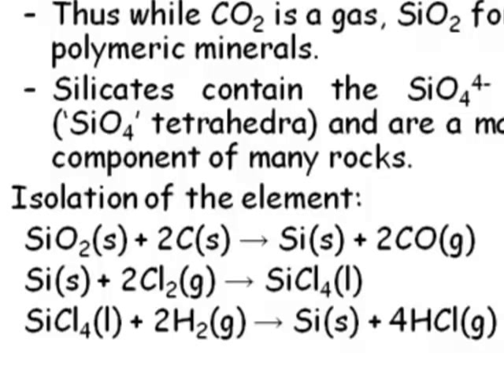Silicon is a very high melting material. You can't really purify silicon very easily. You need an easy chemistry industrial method for purification of your silicon. So what you actually do is you then treat your crude silicon with chlorine. The silicon is in group 14, favours a 4+ oxidation state. You get silicon tetrachloride. So the silicon is oxidised by chlorine to give us silicon tetrachloride.